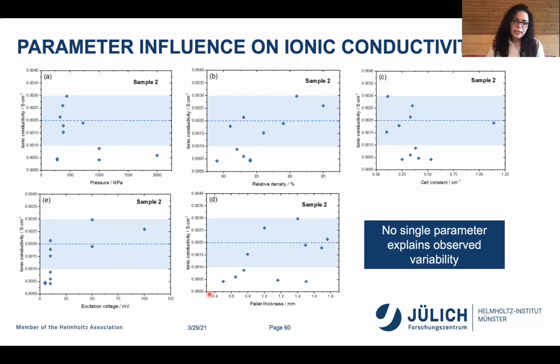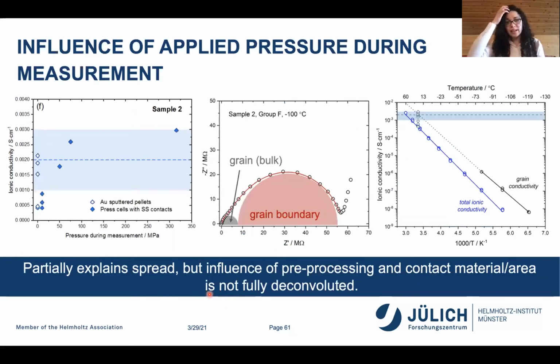What was interesting to observe is the influence of the applied pressure during the measurement. So this seems to be reflected in press cells. These were cells that didn't have any kind of sputtered contacts. As you increase the pressure at the time of the measurement, you increase the ionic conductivity, which makes sense because in situ, you're ensuring better grain connectivity. And this then influences the total ionic conductivity that you extract for your system. But it doesn't fully explain the variability that we observe with pellets that were sputtered, let's say, with gold contacts. So it partially explains it.